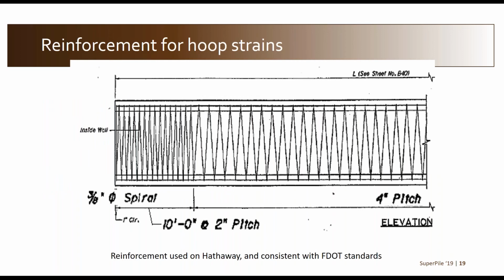We all know that in reinforced concrete, we design the concrete to take compression, and then we add steel to carry the tension. So hollow cylinder piles are no exception. They usually have a spiral transverse reinforcement detail like shown here. This is a standard plan pile per the FDOT spec, just used straight out of their spec book for this project, the 5-foot diameter pile. At the top, where you have stress concentrations from driving, they have a tighter spacing on the spiral. So it's a 3/8 inch diameter spiral, and for 10 feet, they're at a 2-inch pitch, and then in the center of the pile, it's at a 4-inch pitch. So there was no longitudinal cracking observed at the top, whereas in the middle at the larger pitch, that's where the cracks were observed. So the transverse reinforcement seems to come into play here, as you would expect, because we provide reinforcement, again, to have strength in tension.